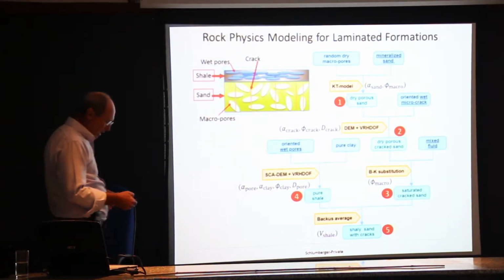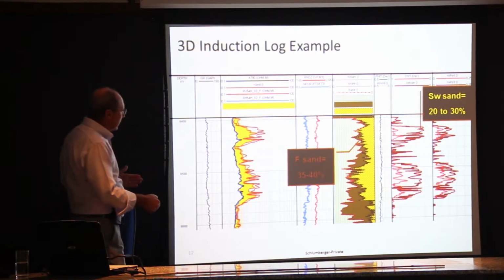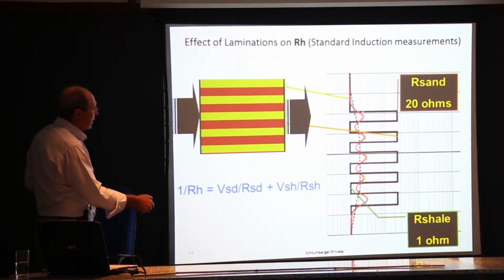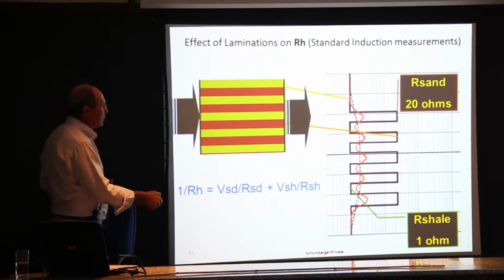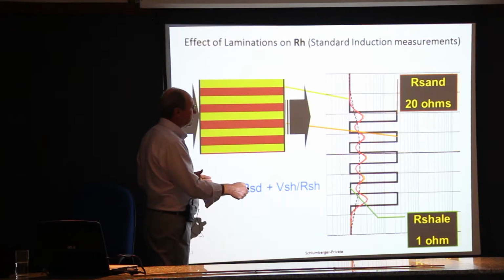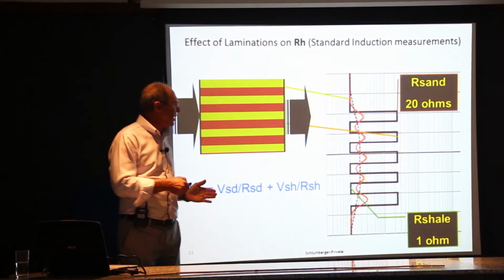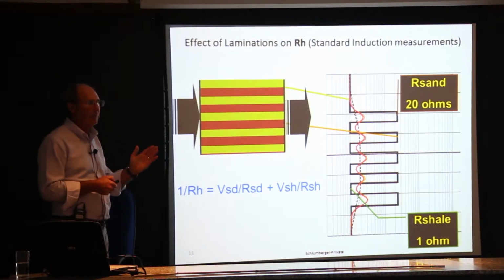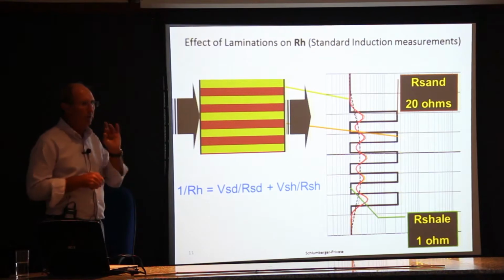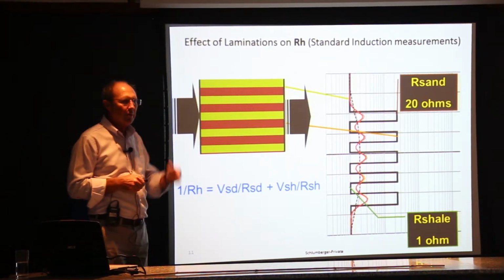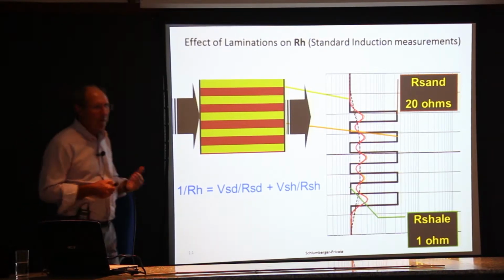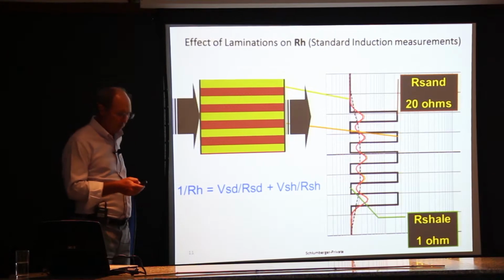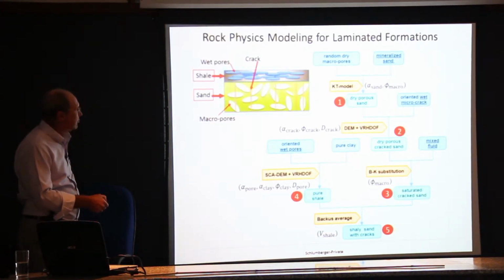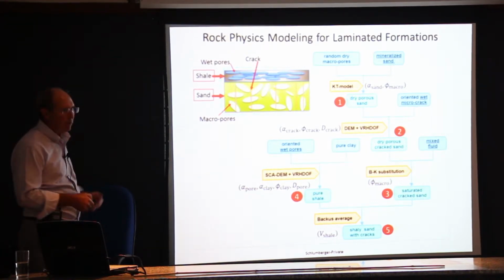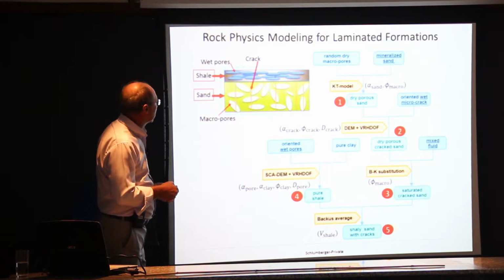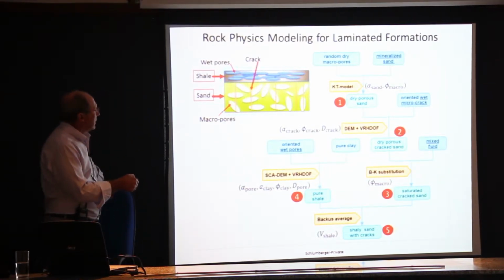But one problem we have still today is you might have a high porosity formation filled with oil, but you could also have a low porosity formation that's not very permeable that'll give you high resistivity. And so using this technique is still difficult to tell whether you have thin beds with oil or if you just have thin beds that are low porosity and high resistivity. And these beds are so thin you can't resolve them with other logs to evaluate their porosity. So what we're looking at now is actually rock physics modeling. And some of you may be familiar with rock physics modeling in laminated formations, where you have different effects.